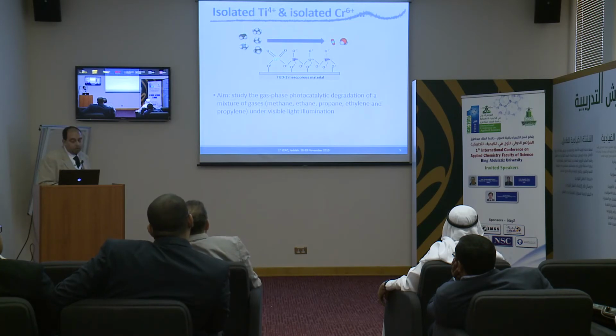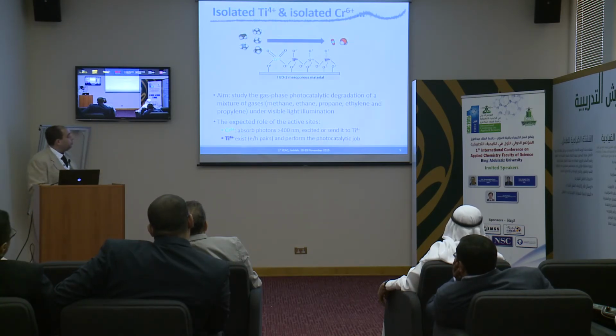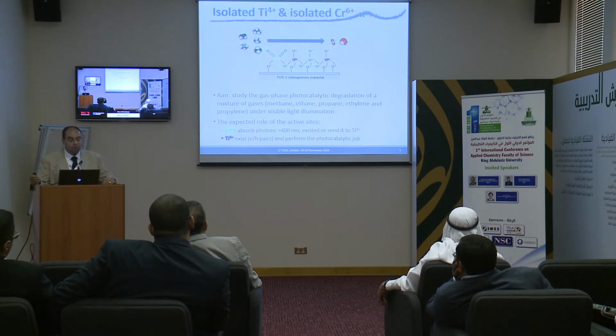So that was the aim of our study, and during the design of our catalyst, we expected the role of chromium-6 to absorb photons in the visible light region, and it can be excited itself or send the energetic photon to titanium-4 to perform the photocatalytic job. Well, actually, if chromium itself can work as a photocatalyst, why don't you just use it without adding any titanium? It's quite simple.